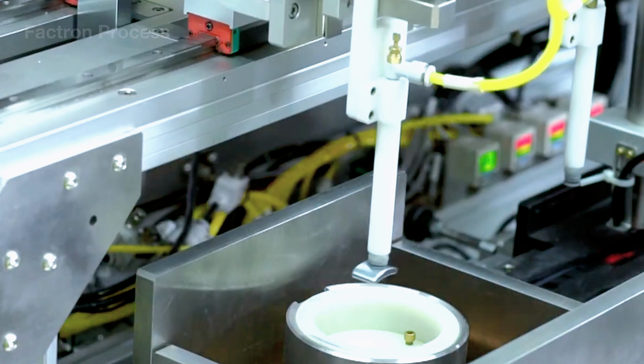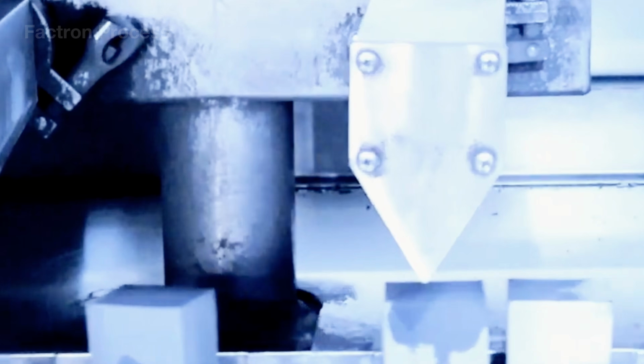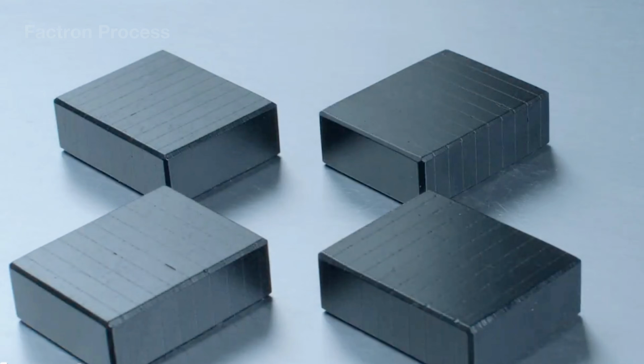For complex parts, material losses can reach 30 to 50% of the compact's mass and are sent to a rare earth recovery line. The finished pieces are then ultrasonically cleaned, rinsed with deionized water, and coated with Ni-Cu-Ni, zinc, or epoxy to a thickness of about 20 micrometers for corrosion protection.